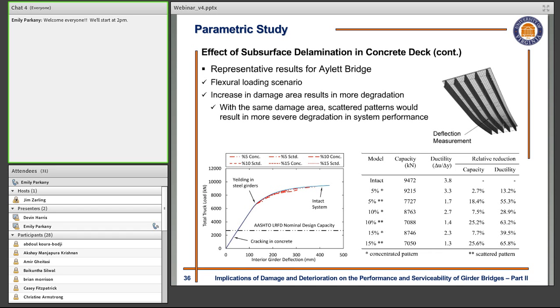What you can see is that generally delamination does not have major impact on the overall behavior of the system. It doesn't have major impact on the evolution of material nonlinearity, including the cracking in the reinforced concrete deck and yielding in steel girders. Other than that, you can see for all cases, we were almost able to capture the same level of ultimate capacity for the system. So there's no major change on the reserve capacity of this system over the nominal design capacity. With no change on the reserve capacity, it means that delamination does not have major impact on the redundancy, and as a result, we can say delamination itself does not have a major impact on the level of safety of the structure.